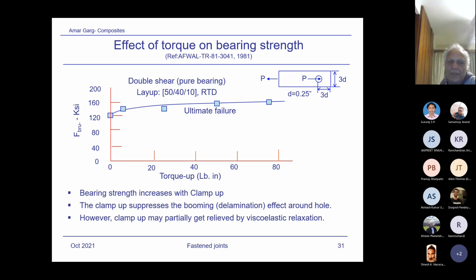So you can understand now the importance of joint clamp up to increase the bearing stress allowable or joint capability. It's very important. When we are designing the structures, I think 2 weeks back somebody asked a question about the relaxation phenomena, and I'll discuss that in this. Suppose the test is showing 160 KSI at 100% torque. But generally, what happens when we are doing the static test of the coupons? We would be applying half the torque, say 40 pounds inch, which will provide us the lower value. And this is the value which we'll use in design.